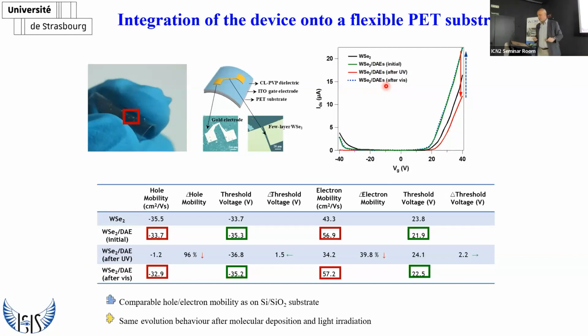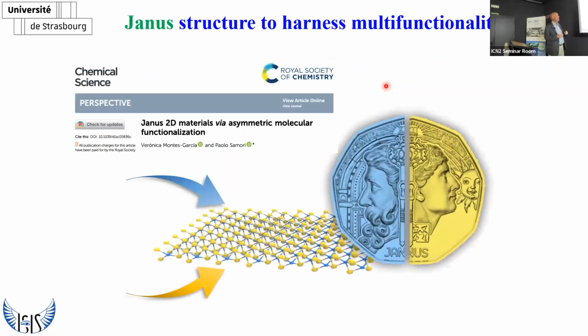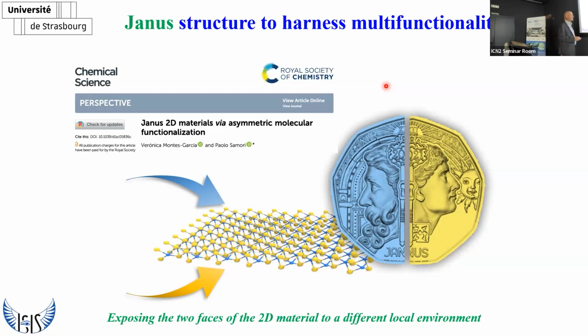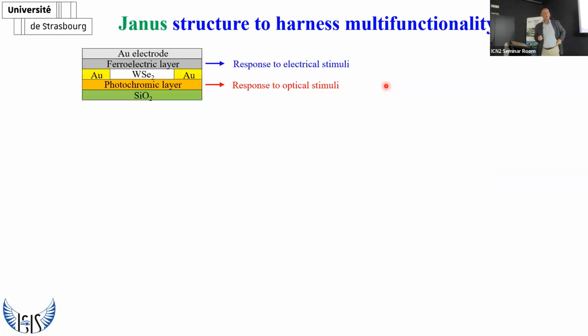Okay. So now this of course can also be supported on a flexible substrate. You can do different types of bending cycles, and this kind of photoresponsiveness is retained. Now the last part of this multiresponsive electronics is related to a thought. The thought is that the material is perfect because you can create very controlled interfaces with the top and the bottom surfaces of the material. And so we can use a kind of Janus approach to harness multifunctionality by exposing the two faces to different local environments. And that is what we have done.